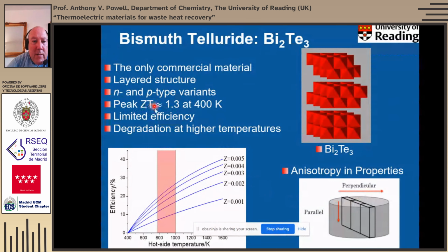And the reason that this ZT is important is it feeds directly into the efficiency. So this is showing the efficiency here on the y-axis as a function of the hot side temperature on the x-axis, for different values of Z. So these are Z now as opposed to ZT. Bismuth telluride with a ZT of about 1.3 at 400 Kelvin puts it somewhere between this 0.002 and 0.003 line, but of course we're down at 400 Kelvin. So it means that typically we're talking of an efficiency of only 2 or 3% in most applications.